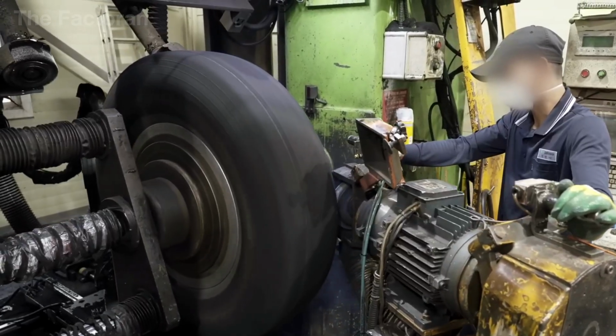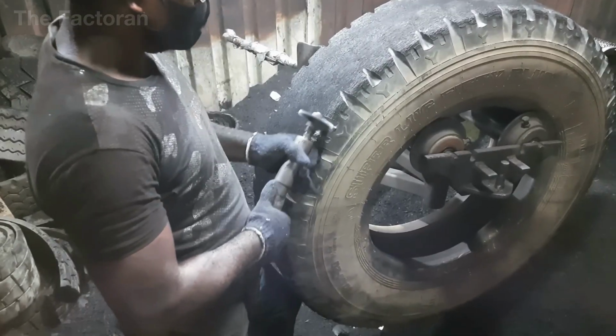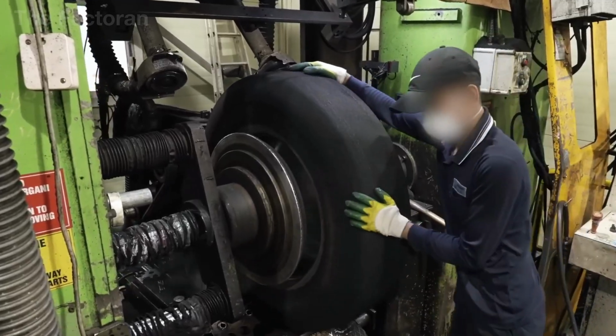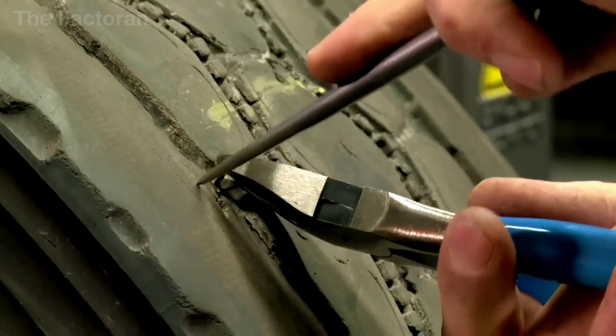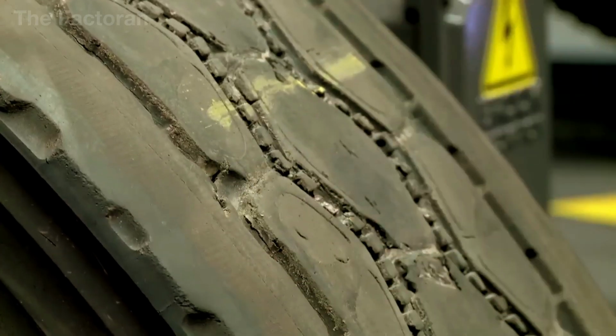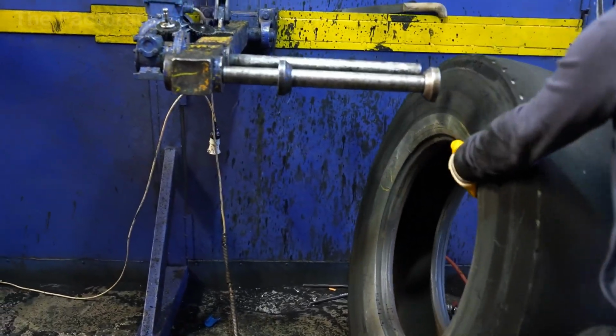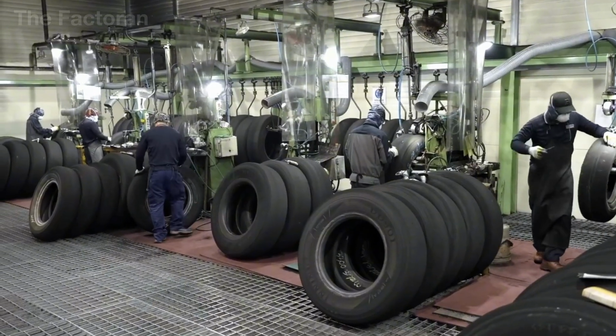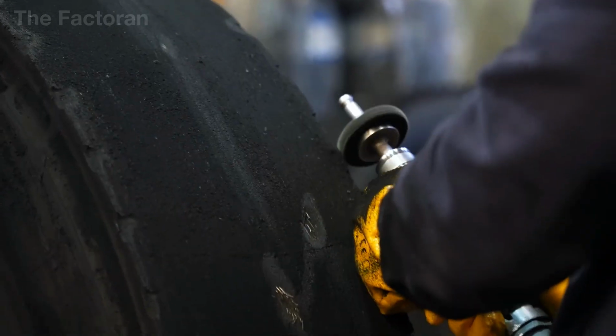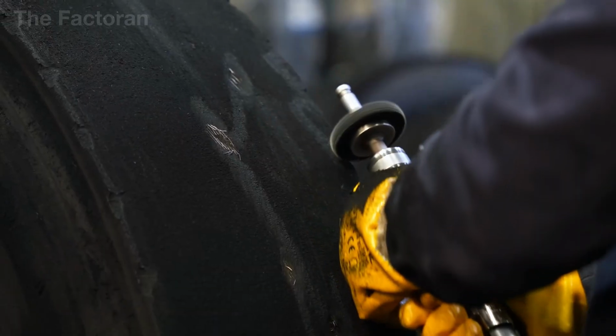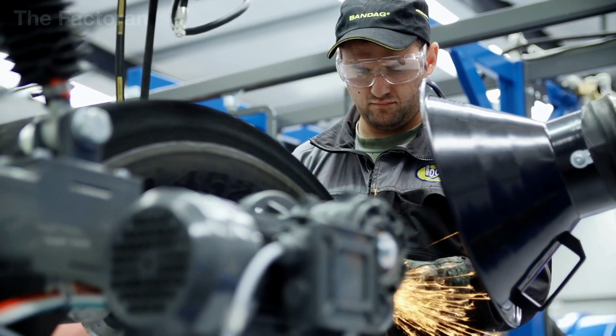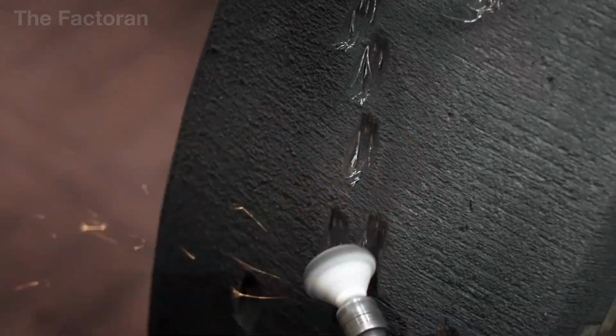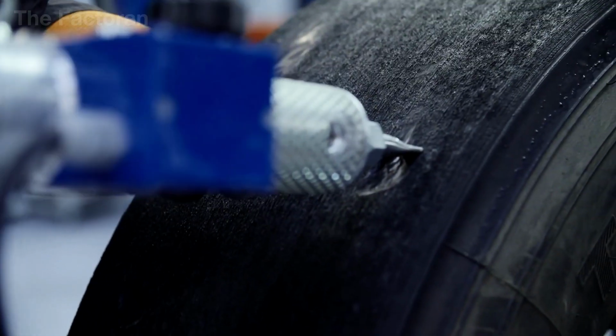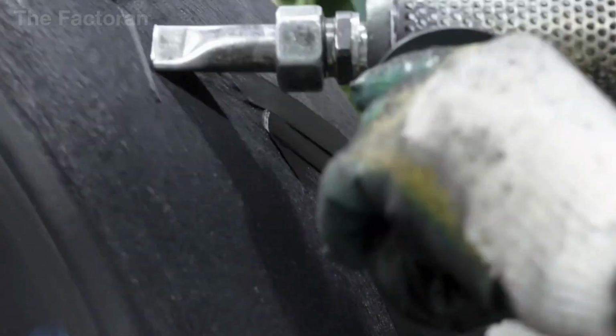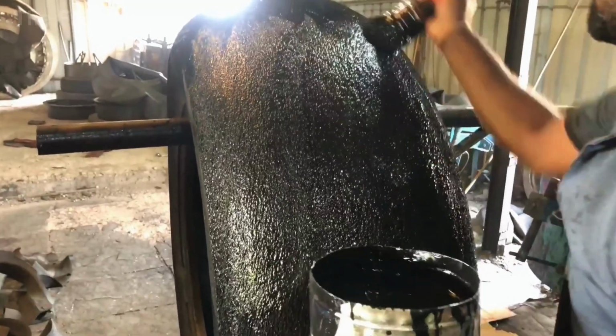After the buffing stage, the tire casing often reveals flaws that the old tread once hid. Things like punctures from nails, cross cuts, or tiny cracks. In the repair stage, workers first drill or cut away the damaged rubber to create a clean, even surface. Then they use liquid rubber cement for small cracks or inject hot, molten rubber directly into deeper holes to fill and reinforce them. For larger damage, a special insert known as a repair patch is heat pressed onto the casing so it bonds firmly with the structure.